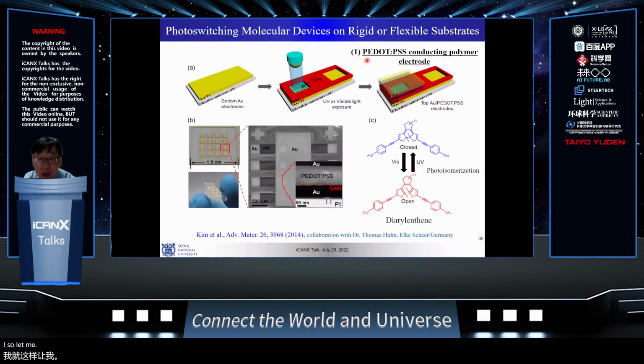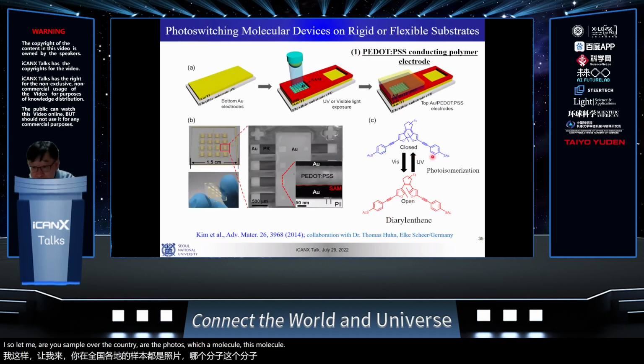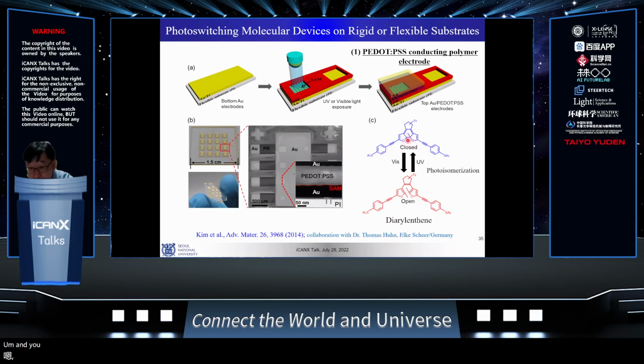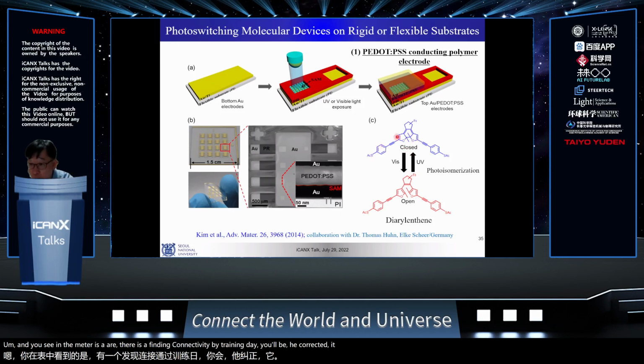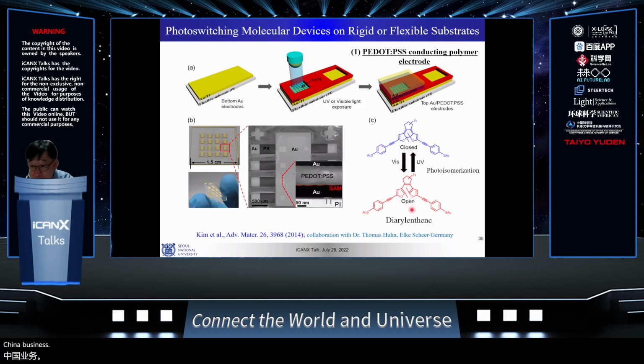So let me give an example of the conducting photo switching molecule. This molecule, the length is about 2 nanometers. The molecule was provided by the German group, and you see in the middle there's a bonding connectivity. By shining UV, it connects, which means overall connectivity is good, so there is high conductivity. If you shine visible light, it disconnects, opens. Then overall connectivity is poor, so the conductivity is lower. So this is on state, off state, as we shine the light.